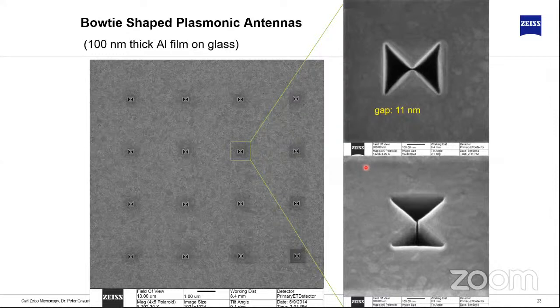And I'd like to show you a little bit about the quality of what we can get with this helium ion microscope when it comes to nanostructuring. So these are bow tie antennas. That's not a very high resolution example. So we have a gap here in the center of about 11 nanometers. But what I would like to bring your attention to is, if you look at the sidewalls, they're perfectly vertical. With a gallium beam, you would typically see some kind of roundness here and some taper angle. With helium and neon, we don't see that. We just have perfect definition of the structures that we have designed in our computer.